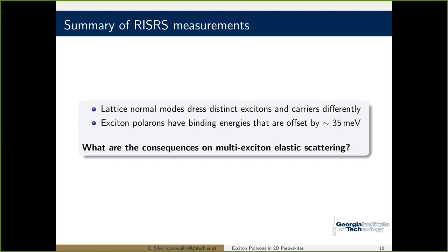These are not spectator phonons, they're active phonons. In the sense that you inject photocarriers, and they drive the recombination of electron-hole into exciton B. And then the non-adiabatic, that means radiationless, relaxation of exciton B to exciton A, which is the emissive state in the LED, is completely driven by these phonons. And so they are active modes. I won't show you that.